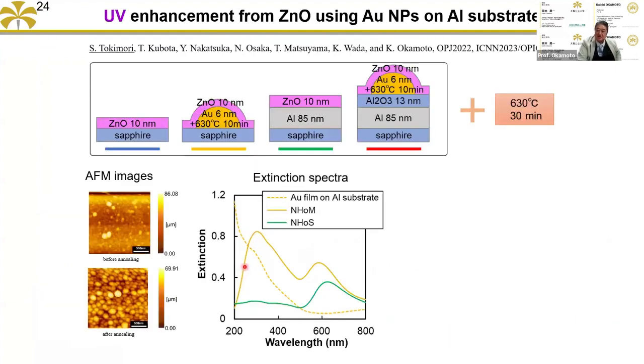On the other hand, gold is very beautiful. By using gold, very beautiful hemispheres were formed. That's why we combined two types of metal: gold for the nanoparticle and aluminum for the substrate. Then we found two resonance peaks. The red light peak is due to the gold nanoparticle, but still it has a deep UV light region.